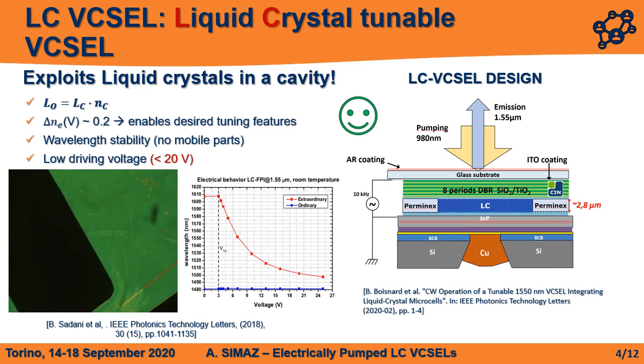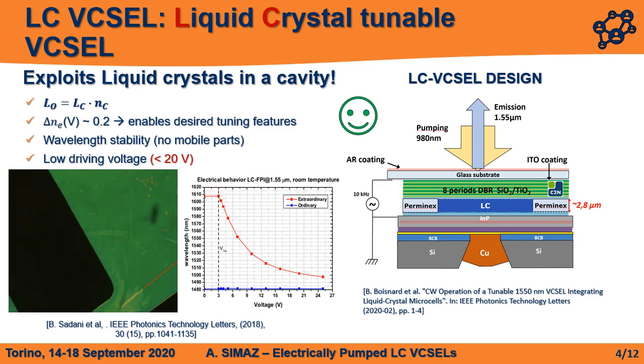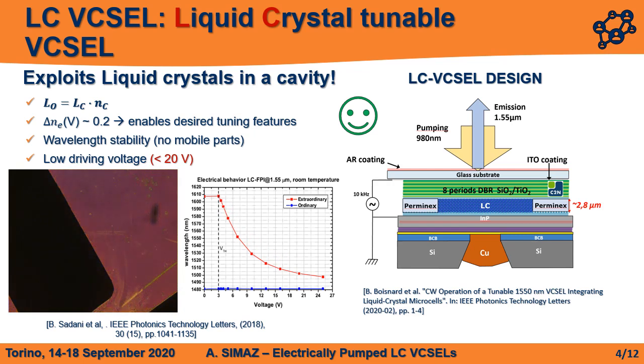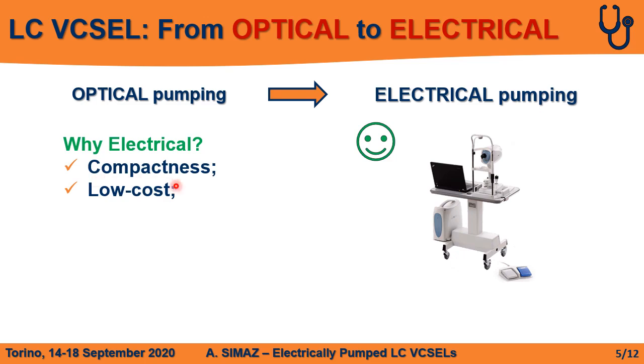As an example, it is illustrated the electrical characteristic of the filter at 1.55 micrometers, showing this phenomenon. Below a certain voltage, called the Fréedericksz voltage, the peak related to the extraordinary refractive index remains unchanged, while for a greater voltage the resonance peak starts to monotonously decrease. The ordinary peak remains always constant. The previous optically pumped liquid crystal pixel design at 1.55 micrometers was presented as a proof of concept. Now, our next goal is to pass from optical pumping to electrical pumping, in order to achieve the compactness and low cost requirements that result in a portable OCT system.